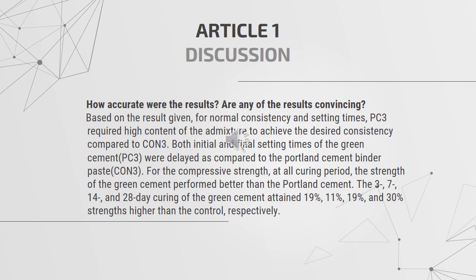For the next question: how accurate were the results? Are any of the results convincing? Based on the results given, for normal consistency and setting time, PC3 requires a high content of admixture to achieve the desired consistency compared to CON3. PC3 is green cement and CON3 is Portland cement binder paste. Both the initial and final setting times of PC3 were delayed compared to the Portland cement binder paste.